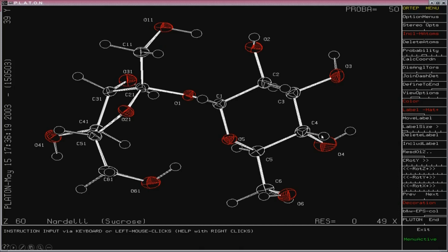The hydrogen atom position therefore now depends upon how the positions of the other atoms nearby change. The other thing which we can do, of course, is once we have the hydrogens identified from the difference Fourier, and if we still have good data at our disposal, then we can try refining the hydrogen positions as well, but refine them with respect to the isotropic value. That is why you see only circles here rather than ellipsoids, because this is now associated with what we call an isotropic thermal parameter.